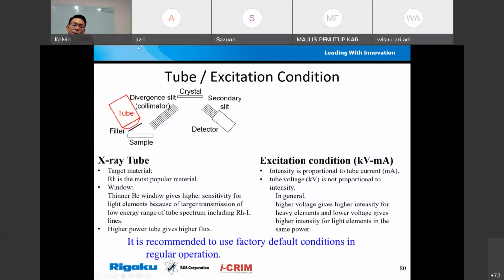One is the tube condition. What it means is we can increase the tube current, meaning you can go to a higher current to improve the intensity. Generally speaking, kV itself doesn't contribute much to the intensity of the system. So increasing the kV itself doesn't really help too much.